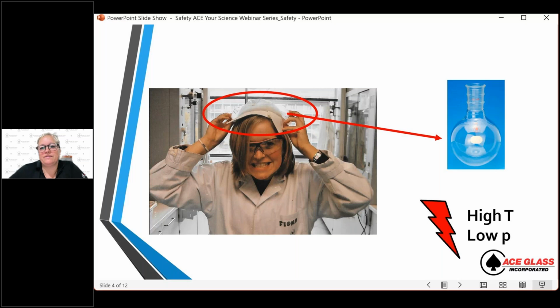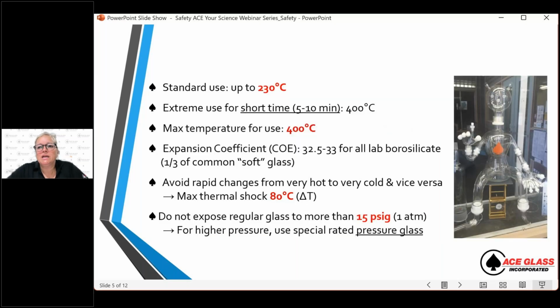But how could this even happen, right? There are a few things we need to consider. Standard borosilicate glass, you should use only up to 230 degrees Celsius under standard pressure. You can use it for short times under extreme conditions of up to 400 degrees Celsius, but that should be the absolute max temperature for your glassware, in order for it not to get misshaped or lose its integrity.